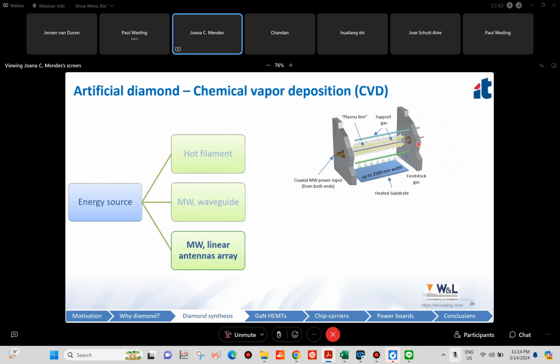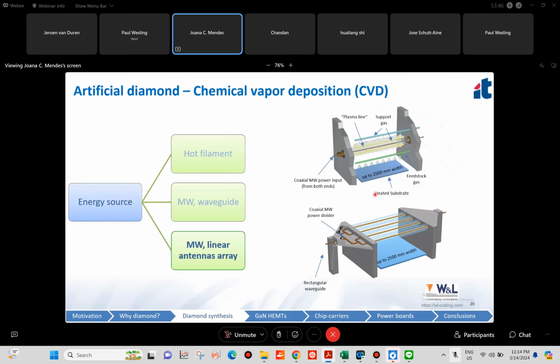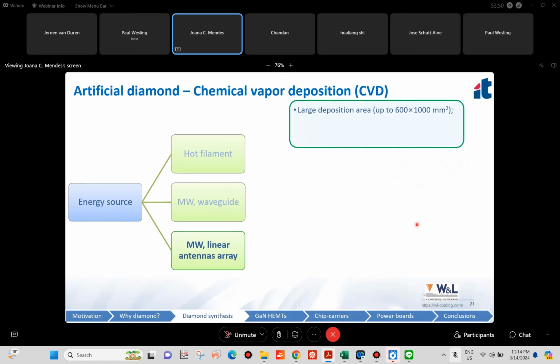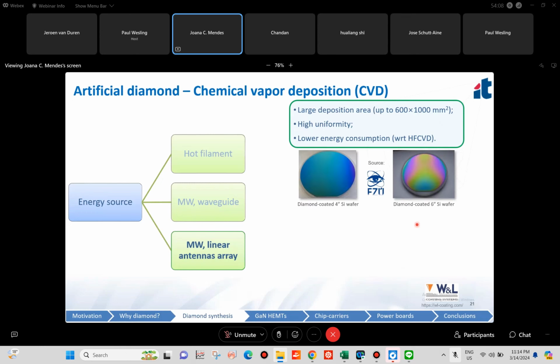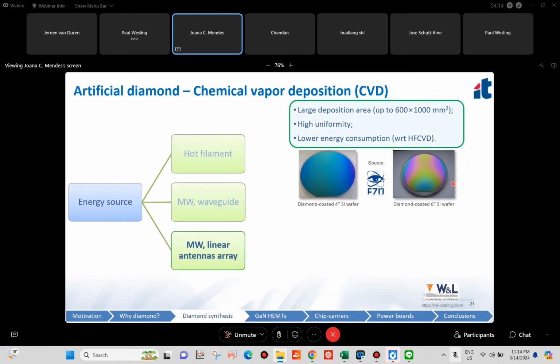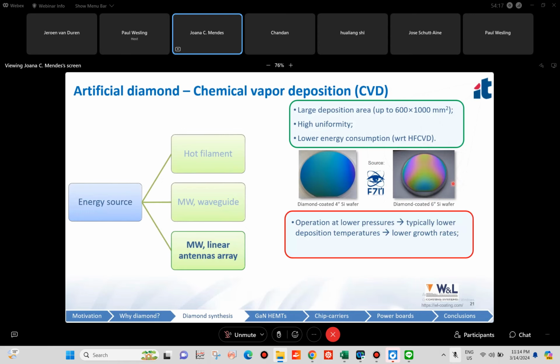And the beauty of this thing is that we can have many plasma lines in parallel, as many as we want theoretically. So we can increase the deposition area up to 600 times 1000 millimeters square. So we can fit many wafers inside such a system. We have a high uniformity all over the deposition area, and we have a lower energy consumption with respect to hot filament CVD. Here you see two coated silicon wafers, a 4-inch wafer and a 6-inch wafer. However, these systems typically operate at lower pressures, so we have lower deposition temperatures and lower growth rates. And we also have smaller grain sizes, so this means that we have a lower thermal conductivity.